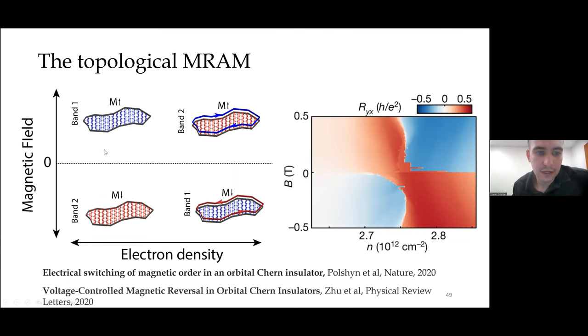What I'm showing you on the left is a plot of the magnetization of the ground state as a function of electron density. In a situation where you have a chiral edge state, you have a gap, but you haven't filled the chiral edge state yet, you'll have purely a spin or non-topological magnetization, an orbital magnetization without chiral contribution. Then as you add electrons, you will reduce the magnetization. And if the chiral magnetization contribution is large enough, you can change the sign of the magnetization associated with each symmetry-broken ground state, right? And if you do that, then you will change what the ground state is at finite magnetic field.